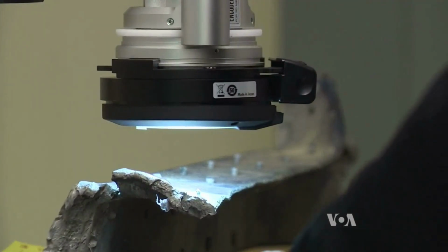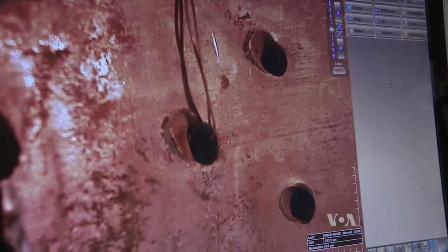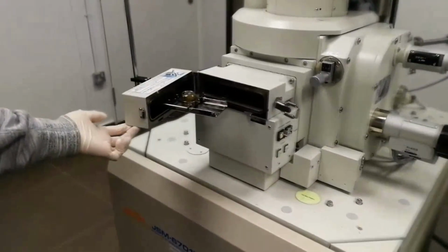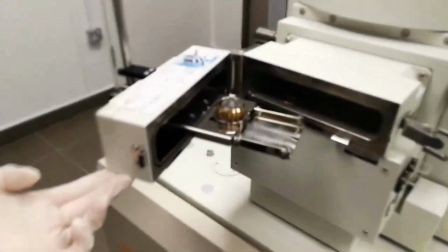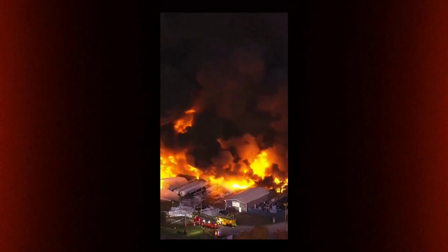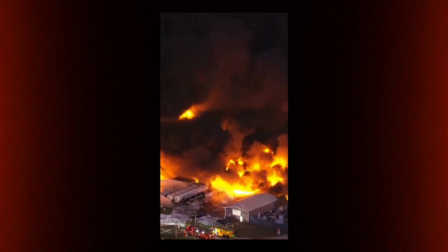Scientists in cleanroom suits laid out the fractured pylon attach fitting, its surface still streaked with soot from the Louisville runway. Under the scanning electron microscope, the metal's story began to unfold. At the heart of the fracture, a crescent-shaped scar traced the path of a fatigue crack, its growth frozen in time by the violence of the crash.